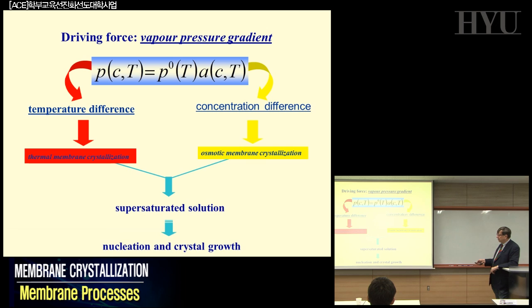And in the supersaturated solution, you can induce nucleation and crystal growth. Crystal growth will not take place in the same part of the system where you have nucleation. That is one of the problems and difficulties in the system: if you don't want to increase the fouling problem too much and lose the transmembrane flux, you have to try to nucleate and grow the crystals in different parts.